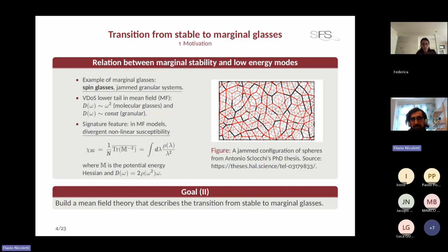Now, in mean-field models of these marginal glasses, the quantity that signals the marginal stability is a diverging nonlinear susceptibility, also known as spin glass susceptibility. This quantity, in the athermal case or at zero temperature for thermal systems, can be related directly to the Hessian spectrum, the potential energy Hessian spectrum. In particular, the lower tail of the distribution of eigenvalues, close to zero eigenvalue, controls the stability of the system. So stable glasses will be characterized by a spectral density featuring a convex power law close to the origin, whereas marginal glasses will be characterized by a spectral density featuring a concave power law close to the origin. So our mean-field theory should be able to describe the transition from a stable to a marginal glass.